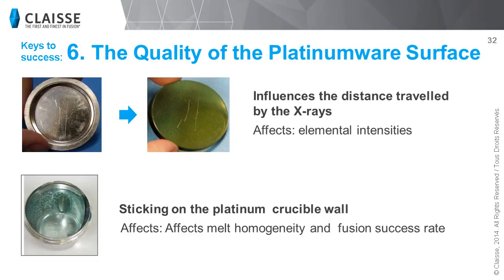In case of sample preparation for XRF, it is important to remember that the mold surface is the perfect mirror image of the final glass disc surface. Any scratches, dents, holes, convexity, or bumps on the mold surface will appear on the glass disc surface. It will influence the distance traveled by the X-ray and affect the elemental intensities. Also, a tarnished or scratched mold will increase the tendency of the glass disc to stick to the mold surface. This could lead to cracked discs.